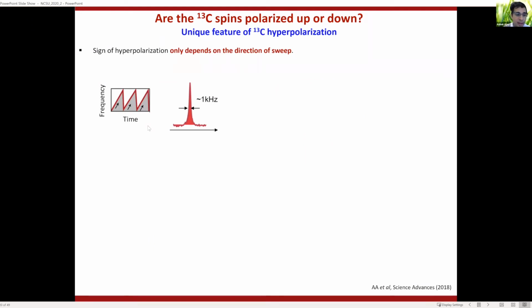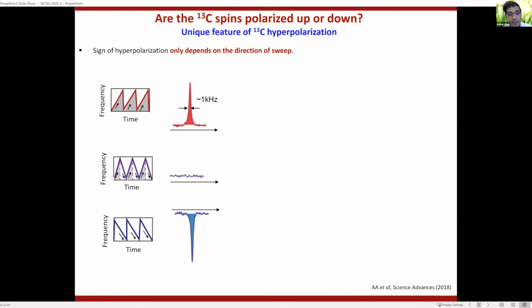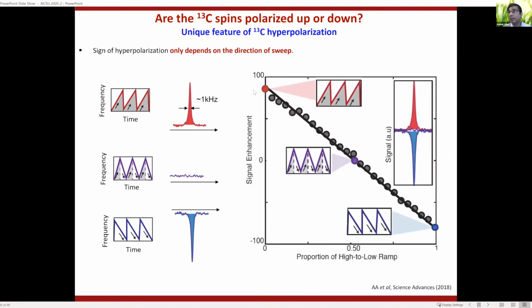I want to show you why that works, but let me just show you some other interesting features of this mechanism. So I told you that you produce spin polarization by swept microwaves. And it turns out if you sweep the microwaves one way, the spins polarize in one direction. But if you sweep the microwaves the other way, the spins polarize in the opposite direction. If you sweep the microwaves in a triangle pattern, the spins don't polarize at all. So actually, you can control the sign of the spin polarization.